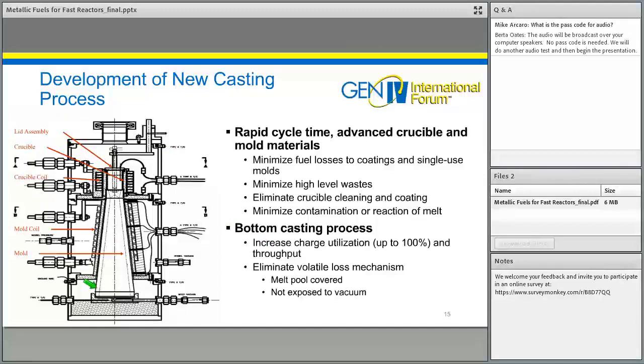So here's an experimental furnace that we developed early on and used for testing and optimization of various things. And you'll see here is the crucible. It's still a crucible that's heated by induction. But now we're going to put the mold pallet down below the crucible. And that benefits you in a couple of ways. First, since you're not bringing in a mold pallet from above, it allows you to put a lid on the crucible and cut off loss by evaporation that way.